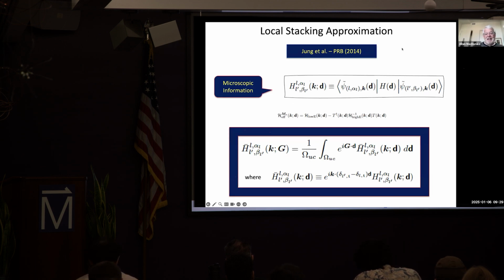So I'm going to talk a little bit about this local stacking approximation, which is certainly the way I think about this. This kind of approach was first used, I think, in this paper in PRB in 2014 for a moiré material formed from a layer of graphene on hexagonal boron nitride. Boron nitride is the 3,5 version of graphene, has nearly the same lattice constant, but not quite the same. And so if graphene is aligned or nearly aligned to HBN, then there's a moiré pattern.